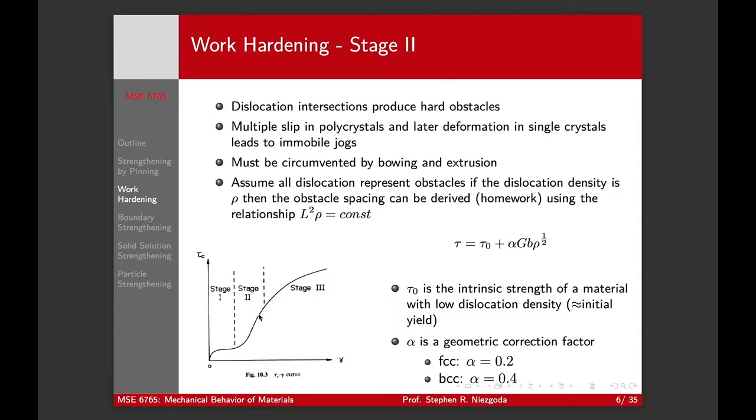And we go from a bunch of parallel dislocations on the same slip system to a bunch of intersecting dislocations to a complex dislocation substructure with a bunch of tangled cell walls that contain a huge number of dislocations and relatively dislocation-free little crystallites in the middle. And that's at the beginning of stage 3.